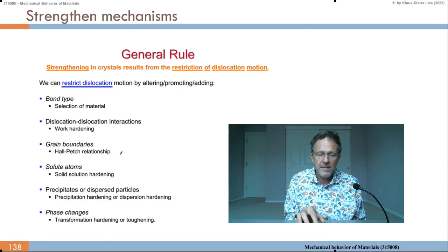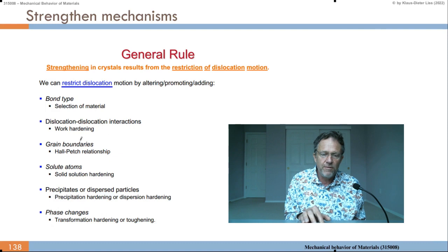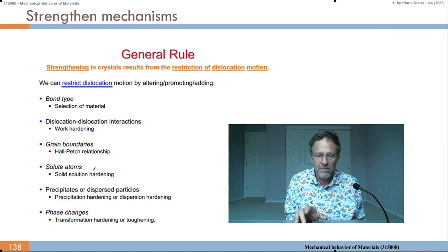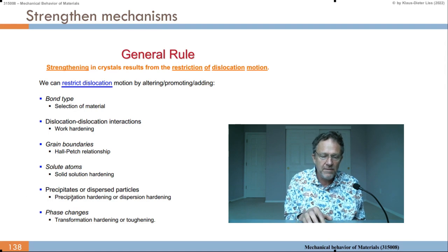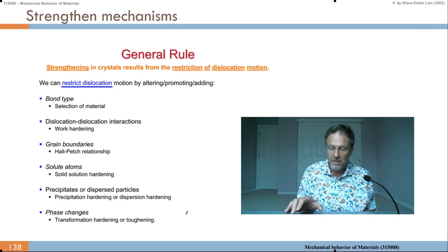Grain boundaries. So the grain size plays a role, because if the grain is smaller, you have more grain boundaries in a given volume. And that gives the Hall-Petch relationship I will talk about. Solute atoms, I just mentioned in the slide before. Precipitates or dispersed particles. So you put something in where the dislocation has difficulty to go around. And phase changes. Transformation hardening or toughening of material.